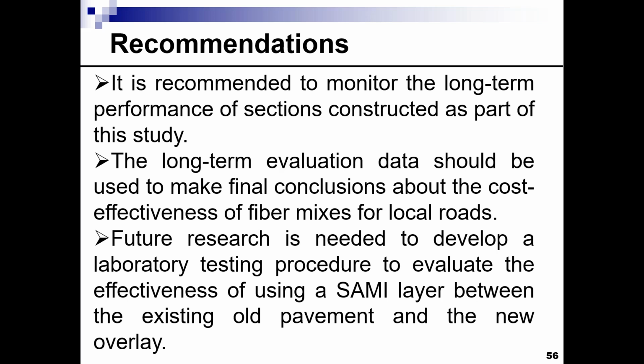We're recommending a minimum of 5 years for those test sections to be evaluated, and the reason for the 5 years is that we're expecting the cracking to start to appear after a few years, and after the 5 years you should see some differences in the cracking intensity as well as extent between the different sections. That long-term evaluation should also be used to make final conclusions about the cost effectiveness of the fiber.